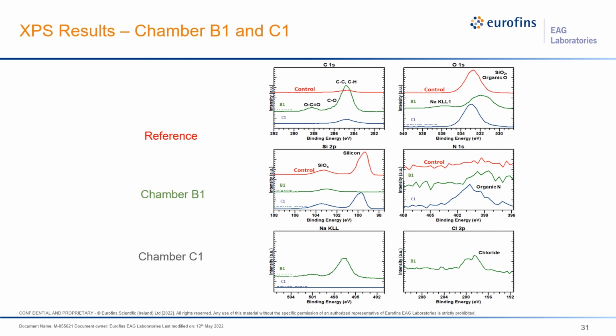And we can see for the control, we have very little carbon here. But on the B1, we actually see a large hydrocarbon peak, a small carbon bound to oxygen, and a small but significant carbon doubly bound and singly bound here. So we can differentiate these types of carbon. And in chamber C1, you can see we just have a little hydrocarbon.